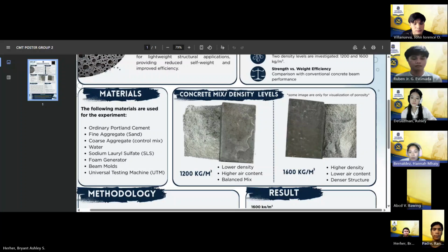For the production of foam concrete, we use sodium lauryl sulfate, or SLS, as the foaming agent. We also use a foam generator to produce the preformed foam before mixing it with the cementitious materials. For molding the specimens, beam molds were prepared to achieve the required dimensions of the concrete beams. Lastly, we use the Universal Testing Machine, or UTM, to test the flexural strength of the beams and evaluate their performance under load. Those are the materials used in our experiment. The next part will be discussed by Mr. Villanueva.